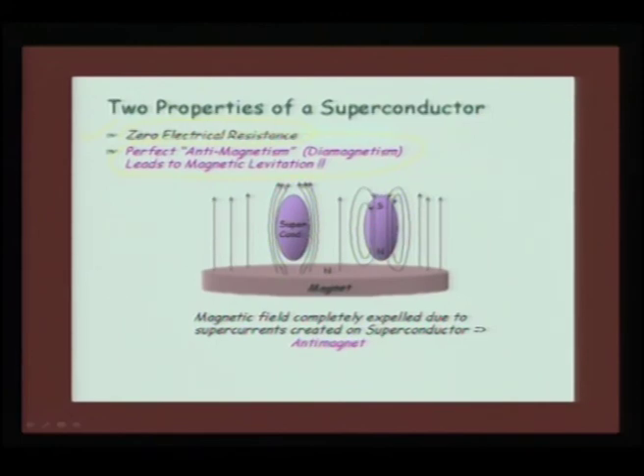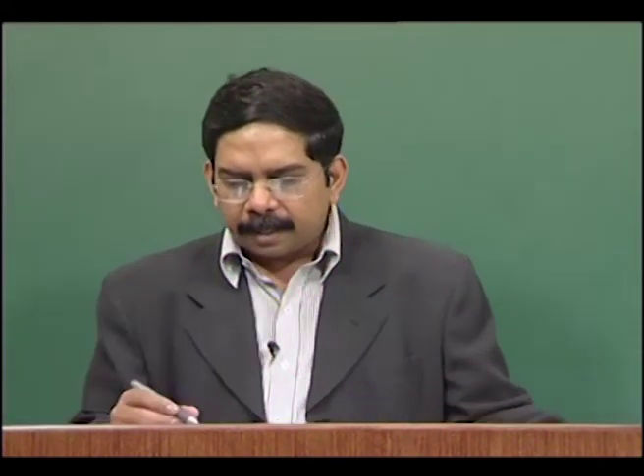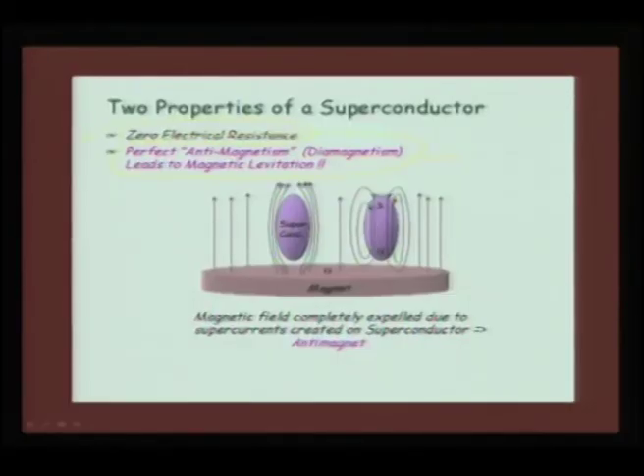In other words, the material may not be diamagnetic at room temperature, but when you are cooling, something happens within the lattice which makes this material a diamagnetic material. As a result, it will expel the magnetic field, and when it is in a diamagnetic situation, that is below the critical Tc point, it is in a perfect diamagnetic state, and in that state one of the manifestations is magnetic levitation.